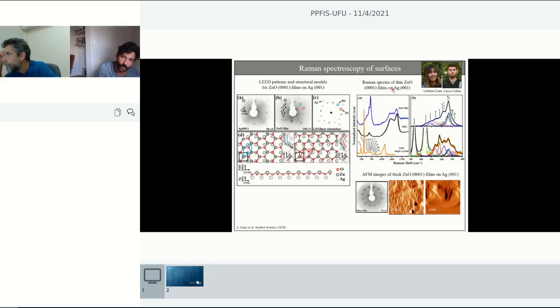And then we built our own Raman setup to study this kind of films. And some of the examples are here, where from the zinc oxide single crystal, we take well-defined single crystals to see what the spectrum looks like. And then we can also perform Raman spectroscopy on a silver substrate, for instance, that's very clean. And then we oxidize this, and then we have the film on top, and we can judge from the patterns that we see, or from the peak positions, what are the relevant contributions to the band and what's the origin of that. So this is some kind of example of the instrumentation that we are doing in the lab.